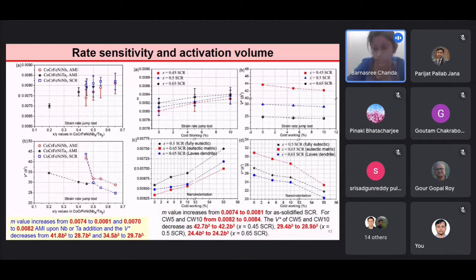to 0.0081 for the as solidified suction casted rod, and for the deformed 5% and 10% specimen from 0.0082 to 0.0084, and the corresponding activation volume decreases from 42.7 to 42.2 b cube and 29.4 b cube to 28.9 b cube for 0.5 suction casted rod, and for 0.65, 24.4 b cube to 24.2 b cube.